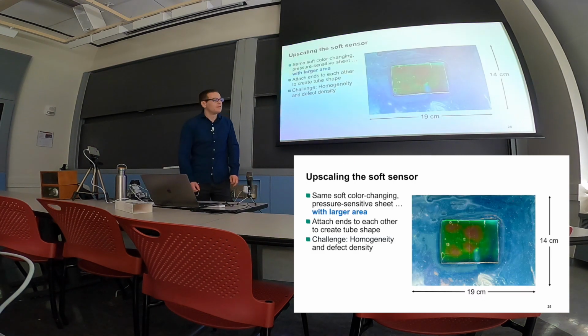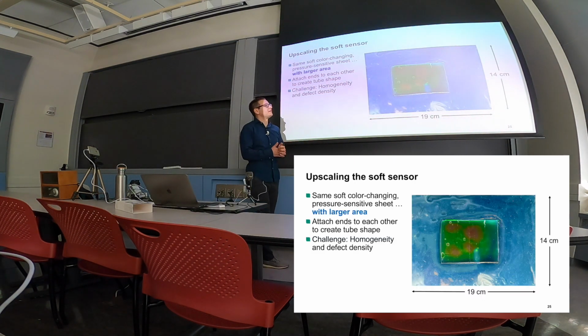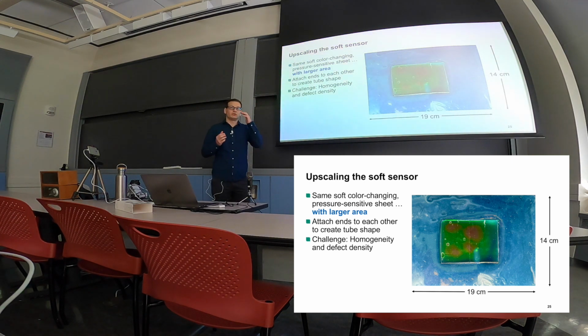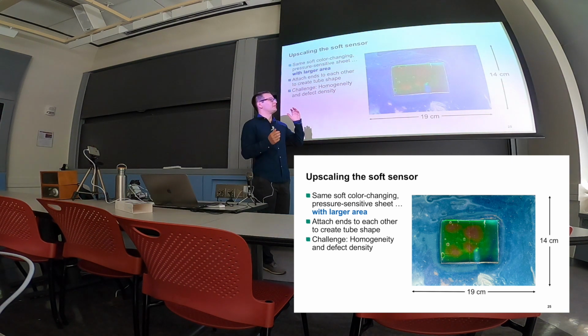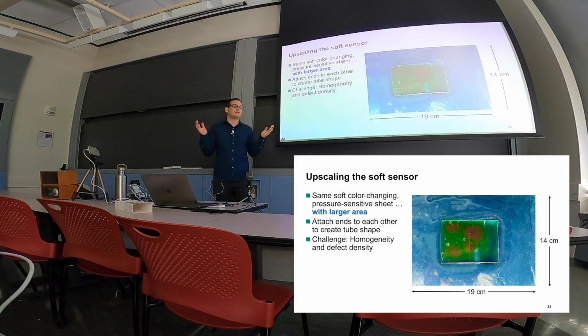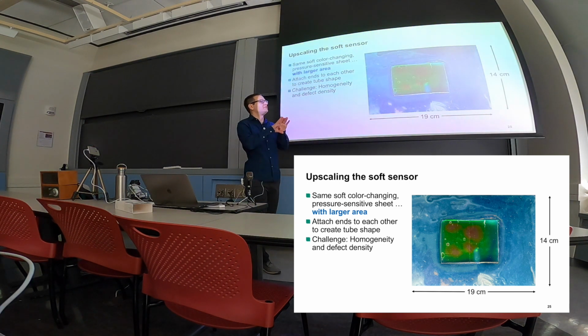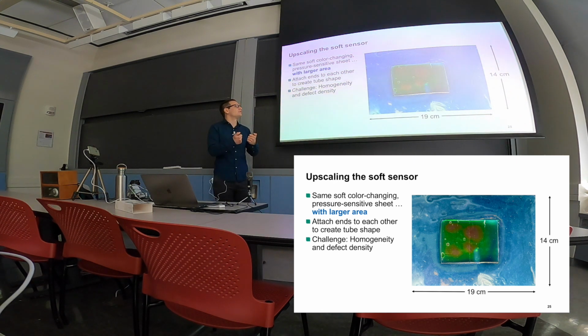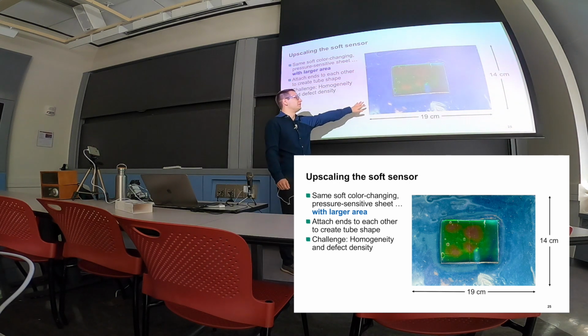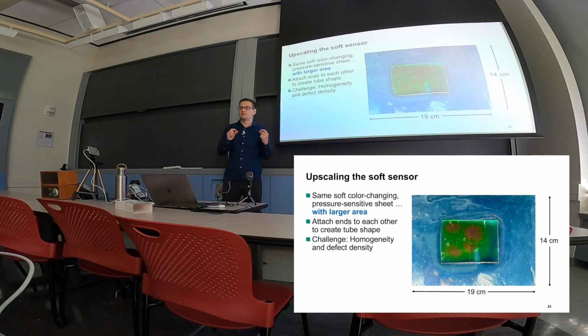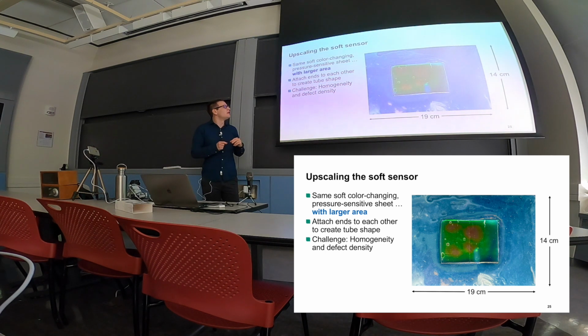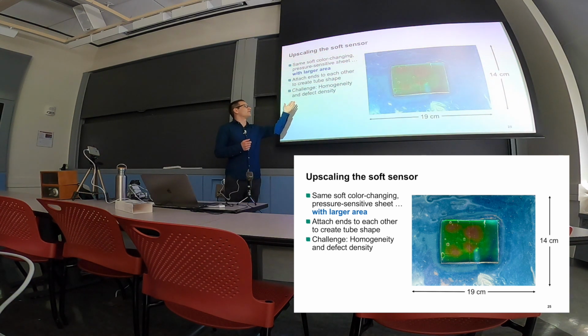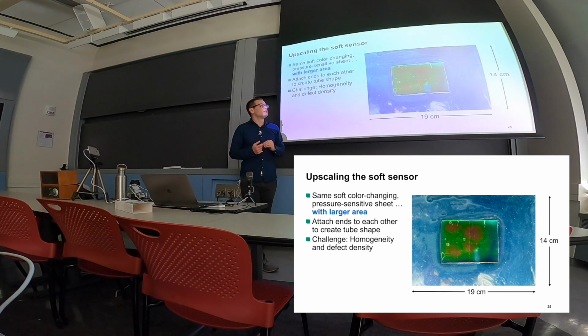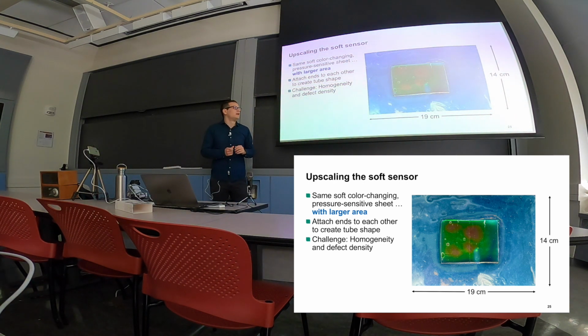And for realizing that, the biggest task was to upscale this layer that I showed to you in the previous slides, so to make it possible to create a huge layer out of that, and then attach the ends of those layers to form a tube, and then wrap it around another acrylic tube to have that whole system. And the biggest challenge in doing that is to make sure the layer is still homogeneous enough, because otherwise we have different thicknesses and therefore different pressure when inflating it on top of the surface. And the other thing is to reduce the defect density so that we don't have too many dust particles in there, which reduce the quality of the color that we see.